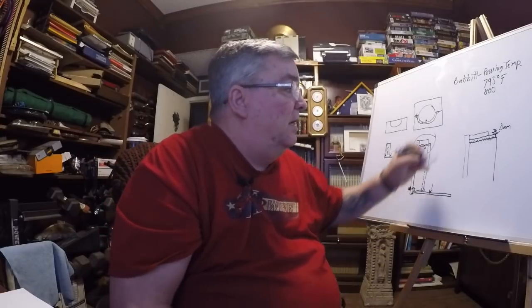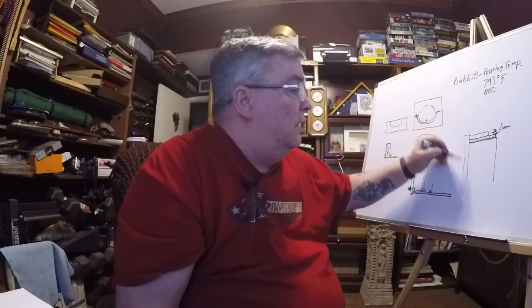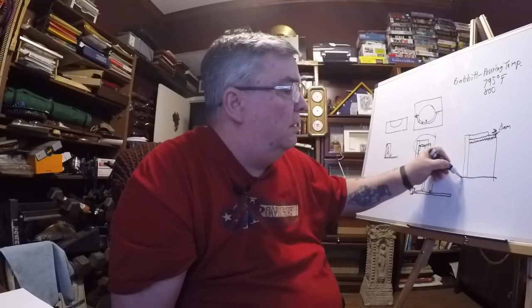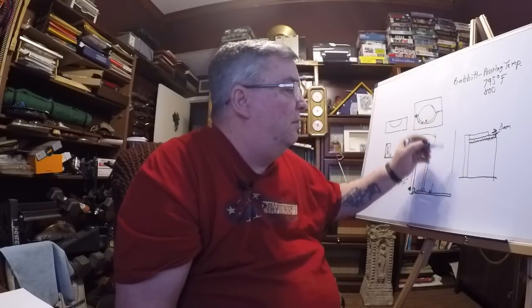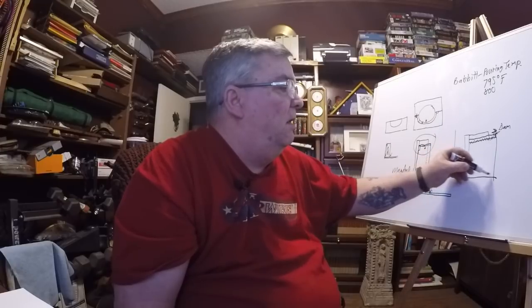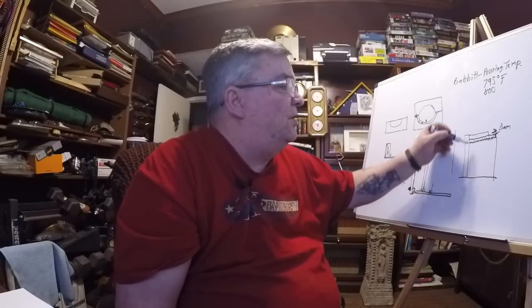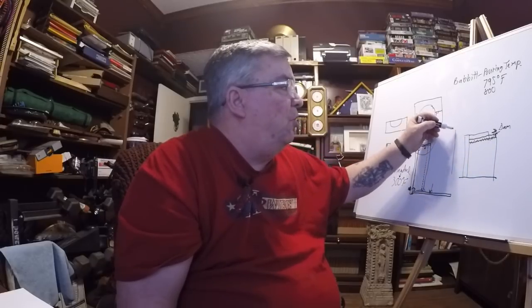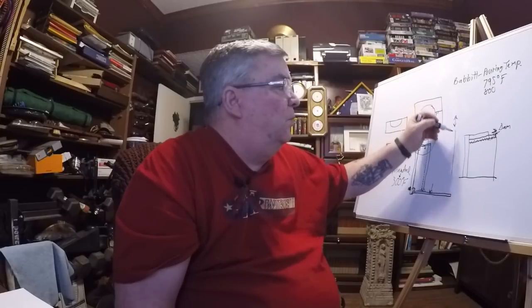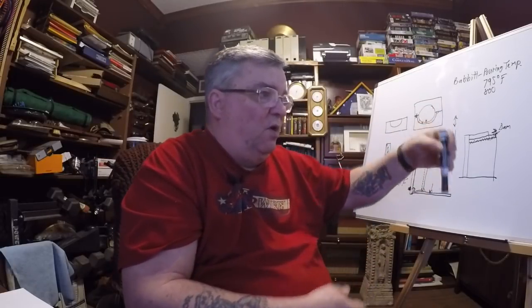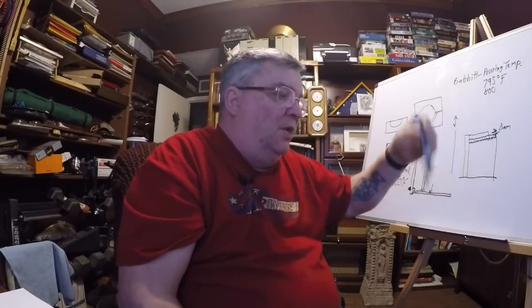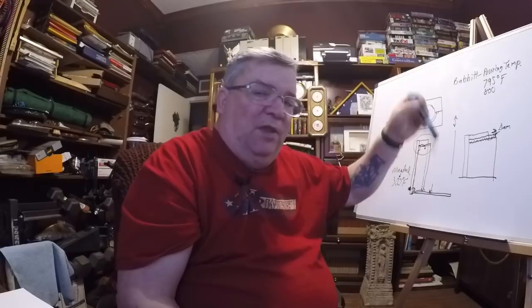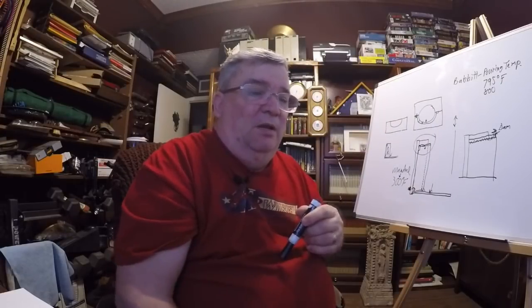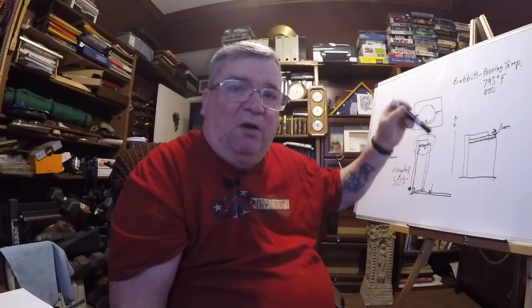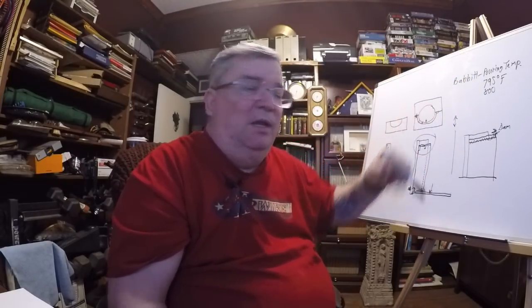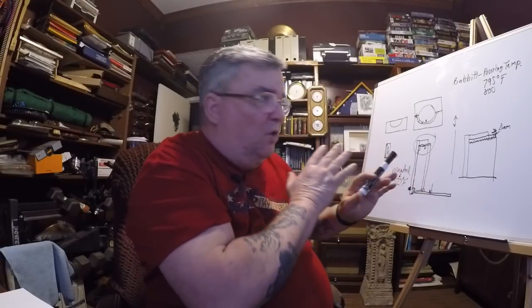You take a nice skinny rod, put it down to the bottom down here, and until it finishes solidifying all the way up here, you churn it. You hit it on the bottom, and you go all the way around, back and forth, back and forth. And now what you're doing is you're doing two things. Number one, you're taking stock of where the solidification is taking place. Okay, everything poured perfectly. There's no leaks, no nothing.